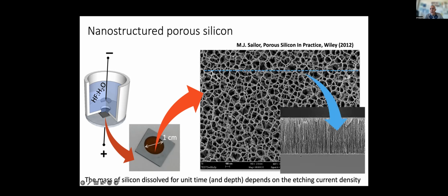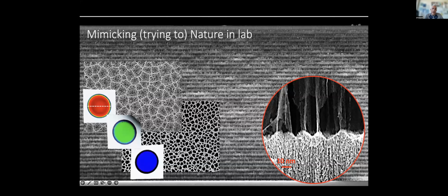And then if the current density is constant over time, I get straight pores. But on the other hand, if I switch the current density between different values during the etching, what I get are two materials with different morphology and then with different porosity. And this means that these materials have different refractive index also, which means I can control the light propagation within these materials in a very easy way. For example, by tuning the periodicity of the etching current density and then on the resulting structure, you can see we can nicely tune the color